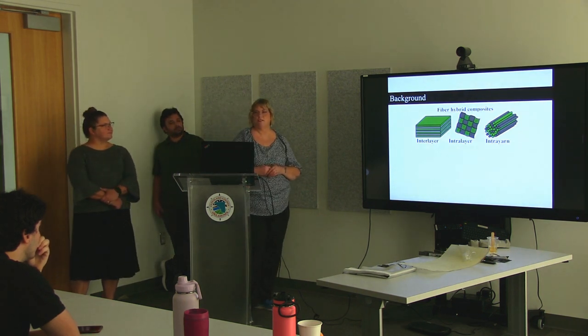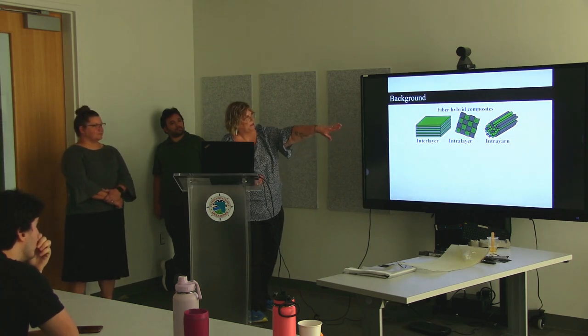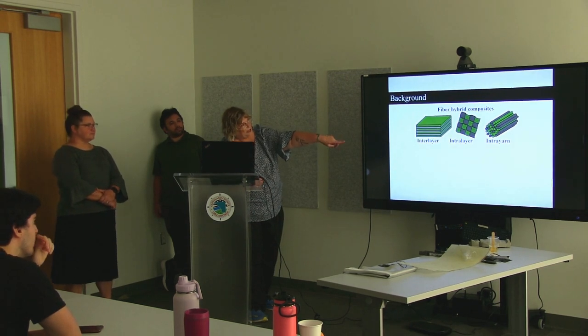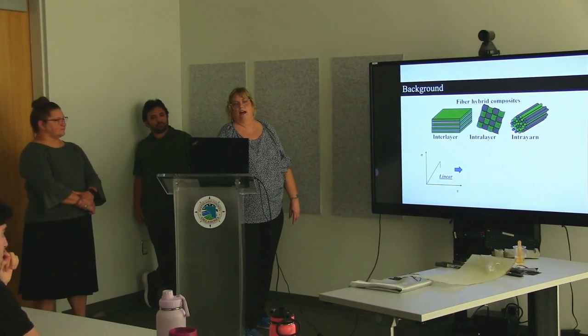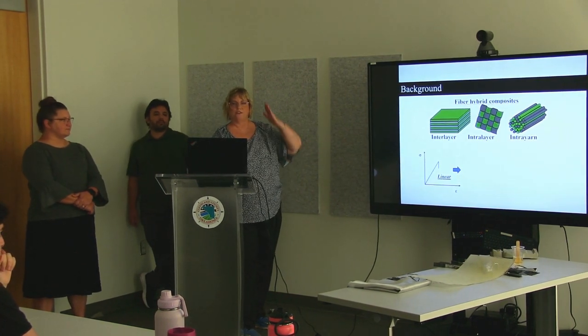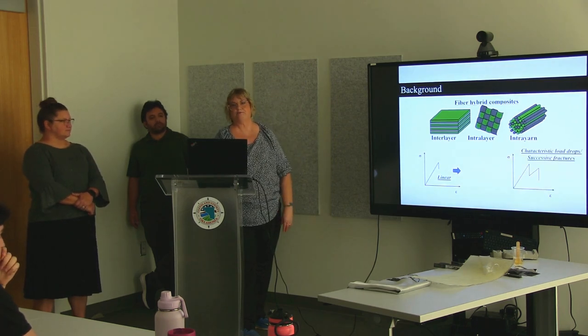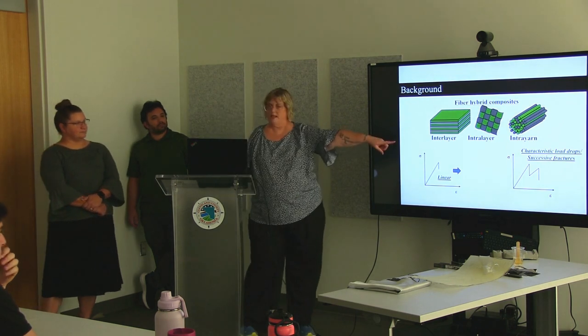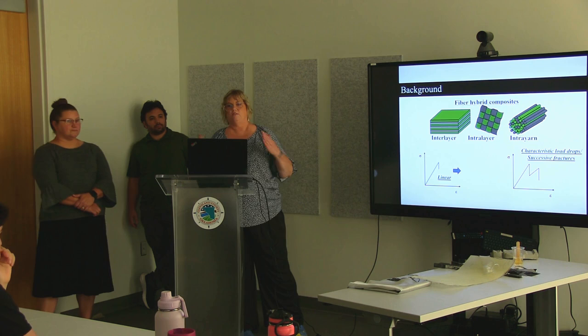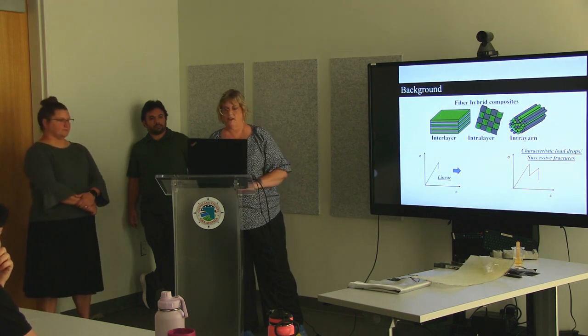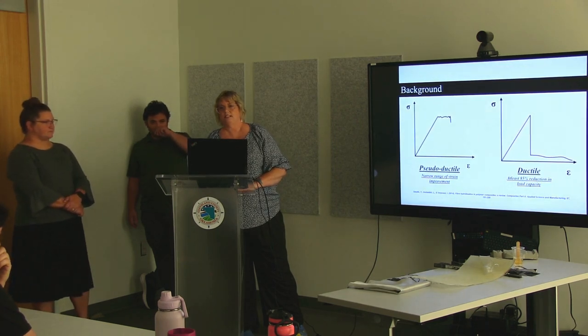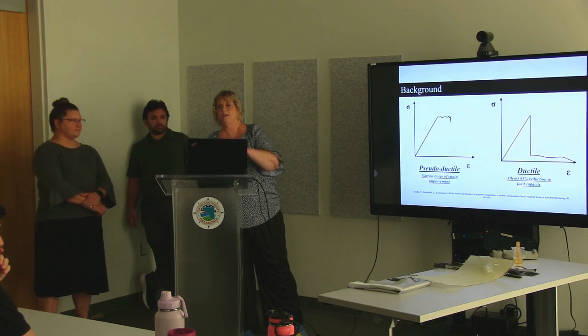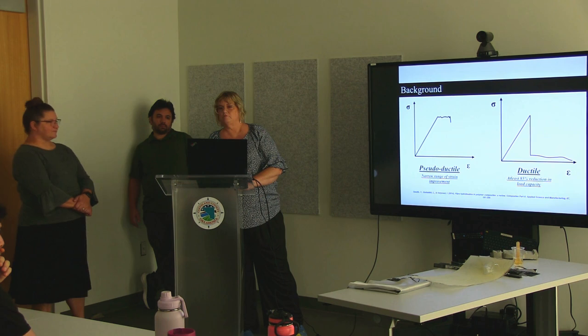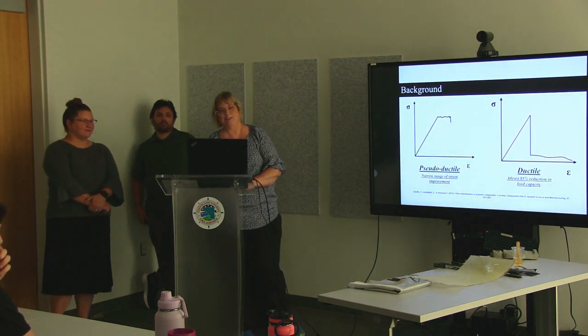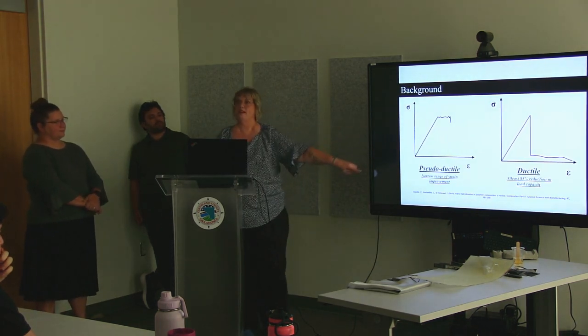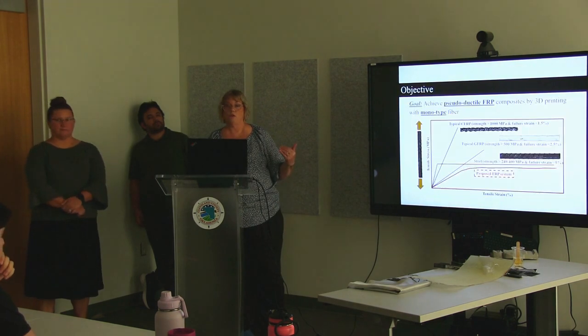So to overcome some of the shortcomings of FRP, there are a few different hybrid composites that they use: interlayer, intralayer, and intra-yarn. A linear breakage pattern looks like that. You get strength as you're testing it, and it suddenly drops off. What we are looking for is the characteristic load drops of successive fractures of patterns that are at different angles or mixed together of materials. Pseudoductility is a flat-topped stress-strain curve on a monotonic tensile test up to failure. If it's not ductile, you get that big break, which could cause some sort of an infrastructure failure all at once.